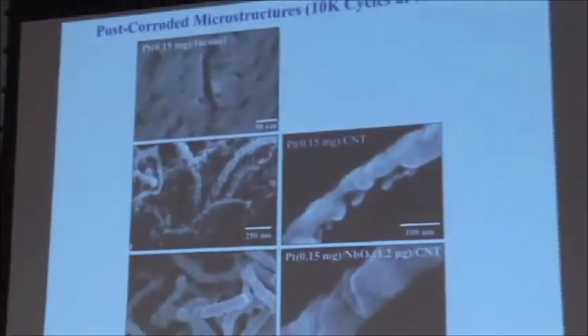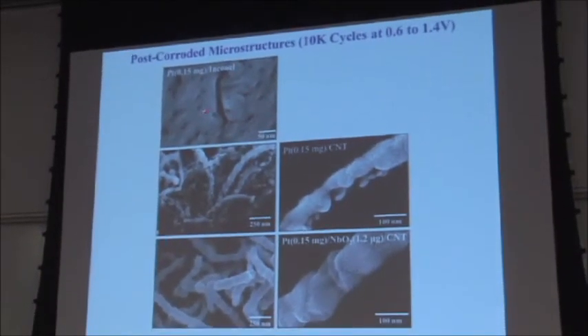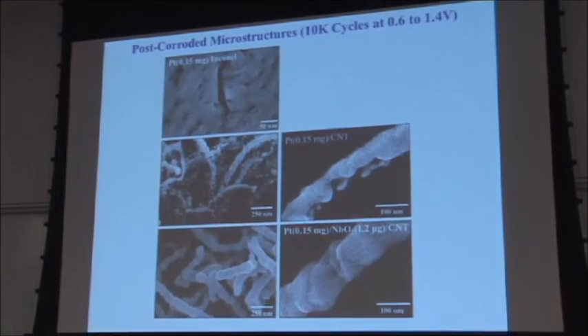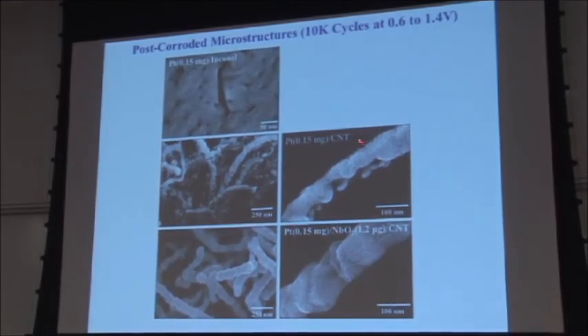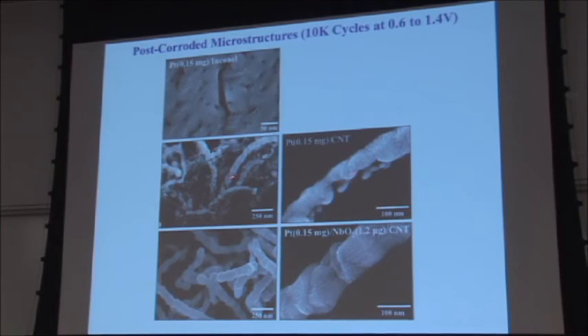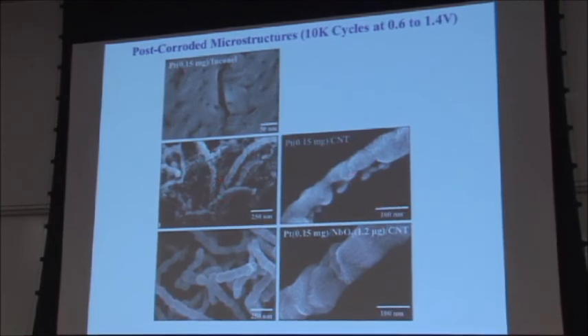And if we actually look at what happens to the platinum during cycling, this is platinum on Inconel planar. Notice you don't actually lose any surface area, but you dissolve all those nice crystallites. So you lose a lot of activity, but basically it's due to loss of these 100, 111, 110 type of facets. This is your platinum on carbon nanotubes. So, pardon the expression, a completely nuked microstructure. Lots of corrosion of the platinum, both from the front side and the back side, and lots of corrosion of the carbon nanotubes. With the platinum with niobium oxide, there's a bit of surface etching of the crystallites.